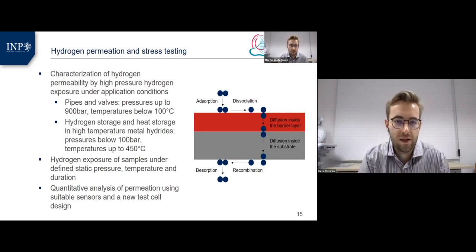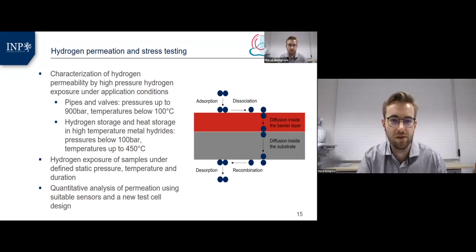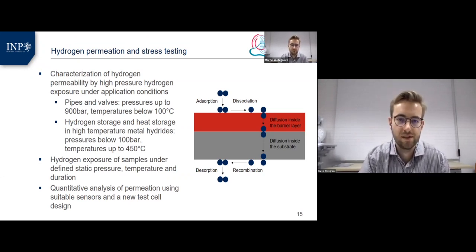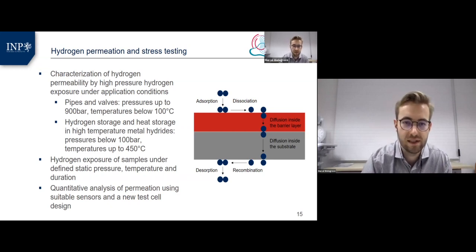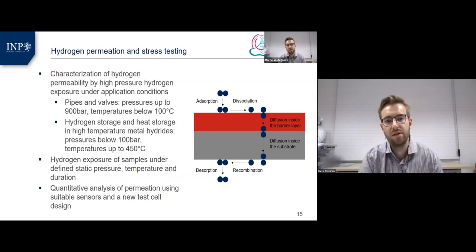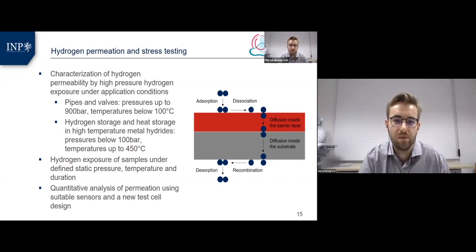And here the most interesting feature, I think, is the ability to characterize these barrier coatings with respect to relevant conditions for applications. So for pipes and valves, these are pressures of up to 900 bars and temperatures, however, below 100 degrees Celsius. Or on the other hand, looking into hydrogen storage and heat storage in metal hydrides, pressures are typically below 100 bars, but temperatures may reach as high as 450 degrees Celsius.